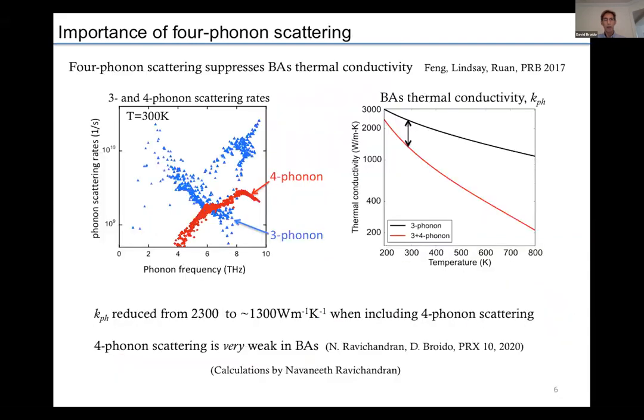But it turned out, as was pointed out by another group, that because the 3 phonon scattering is so weak, that means that the higher order processes, 4 phonon scattering, can actually play a significant role in suppressing the boron arsenide thermal conductivity, as shown in the right-hand plot. And at room temperature, the values that we originally predicted are suppressed down to around 1300 watts per meter Kelvin when including the 4 phonon scattering, which is still an exceptionally high value. And in fact, since that time, our recent calculations on lots of different materials show that the 4 phonon scattering in boron arsenide, while it's extremely important, is actually very weak. And if not for that fact, then the thermal conductivity would have been suppressed a lot more.